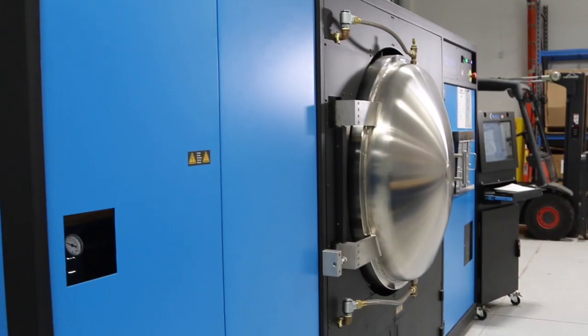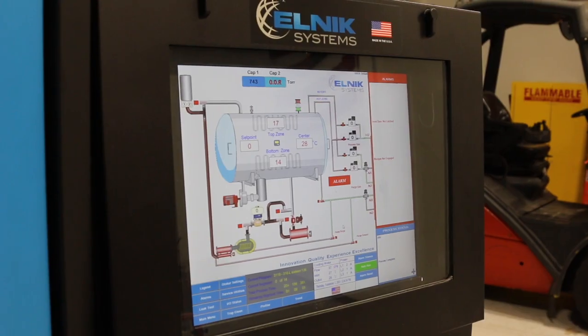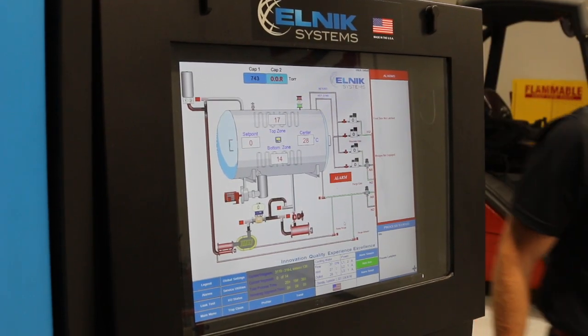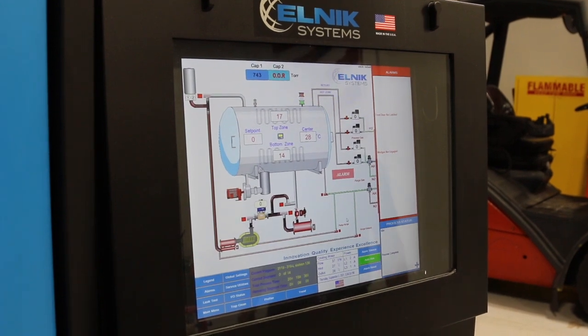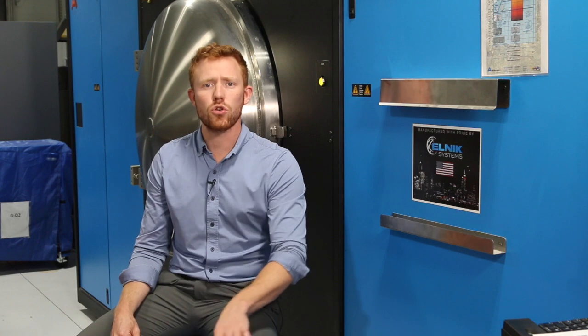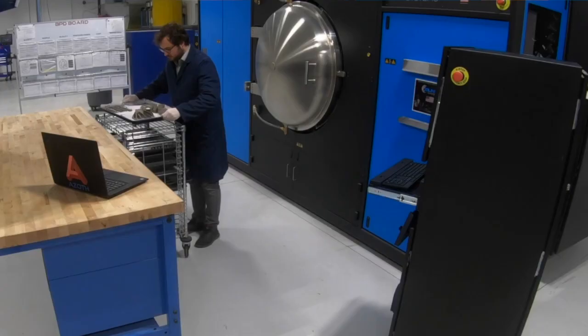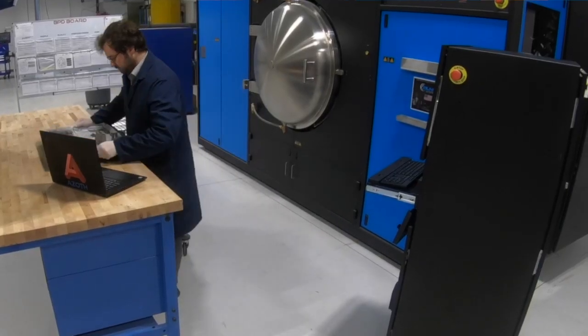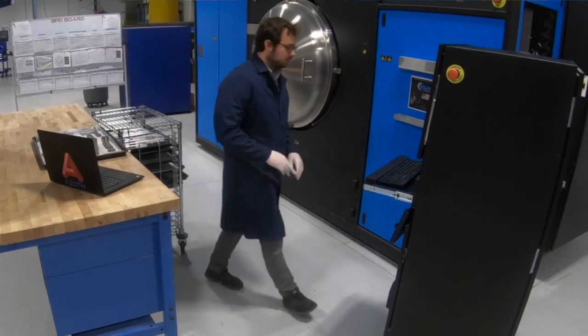In metal-based AM, what we're doing is we're printing a green geometry, roughly 15 to 20% oversized depending on the process and material. And then we go into a process called sintering. In sintering, we heat the parts up to near their melting temperature. We hold for a prescribed amount of time, typically 15 to 20 hours. And then the parts cool down, and what comes out is a fully dense metal part. They shrink about 15 to 20% during that time.